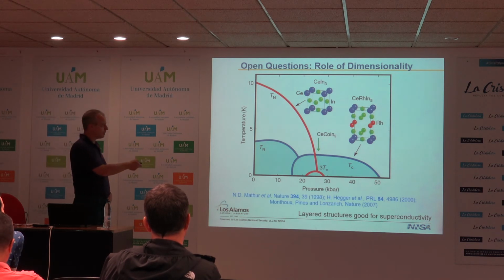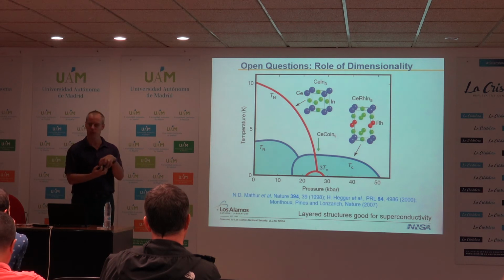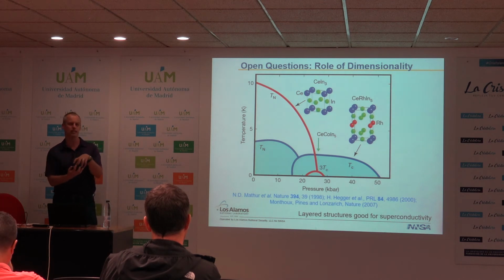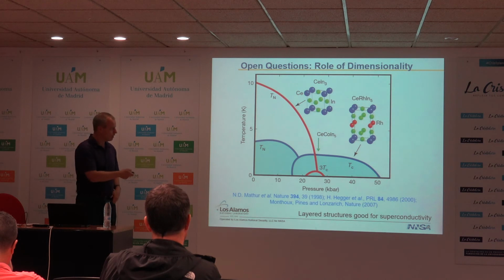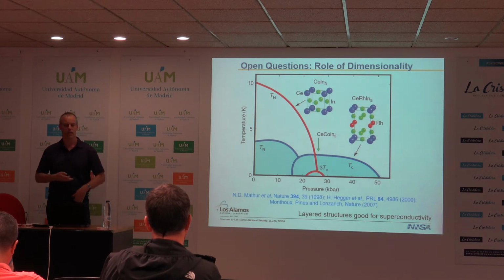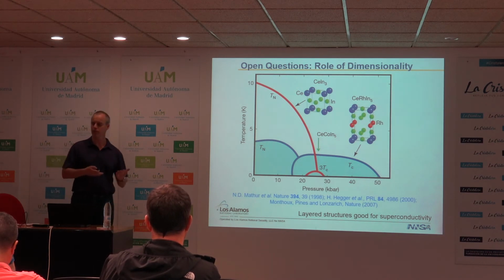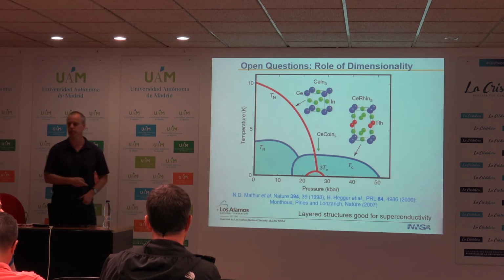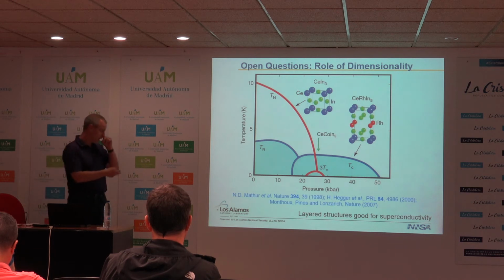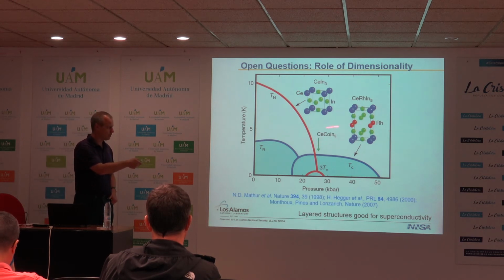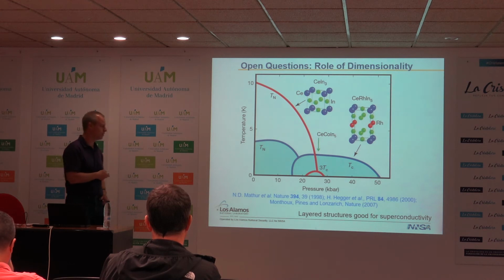The other thing which is nice about this material is cerium cobalt indium 5. If you replace the rhodium with cobalt, cobalt is a smaller atom but isoelectronic, so it effectively acts like chemical pressure on the system. And so cerium cobalt indium 5 is, at ambient pressure, a 2 Kelvin superconductor, whose normal state actually shows non-Fermi liquid behavior and evidence that it's very close to the antiferromagnetic quantum critical point that you expect in the rhodium compound. So a lot of work on the superconductivity is really focused on this material, cerium cobalt indium 5.